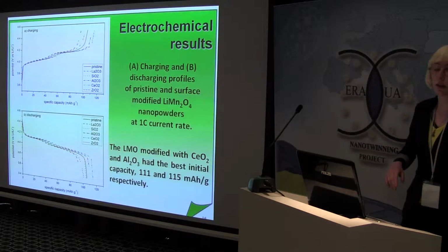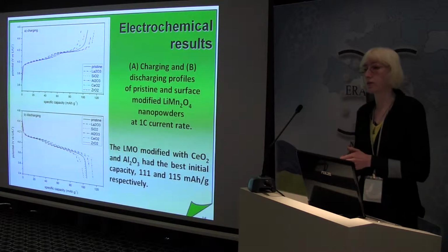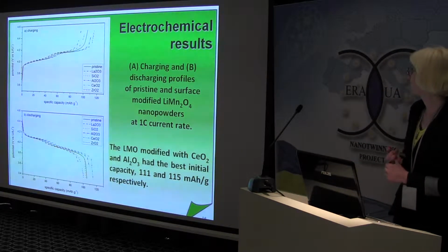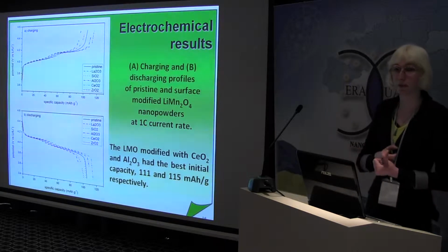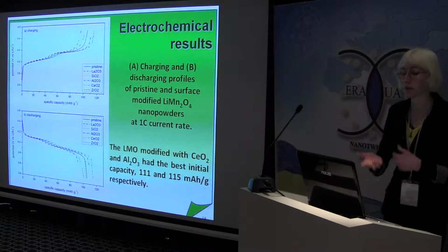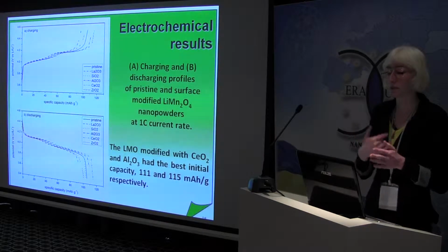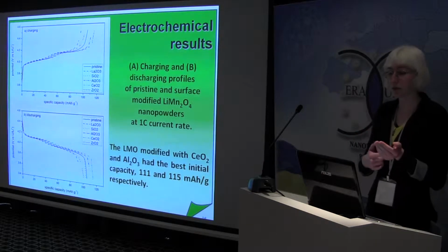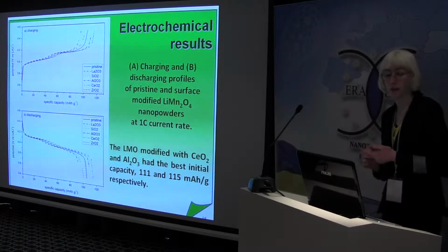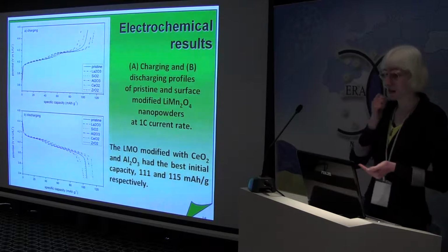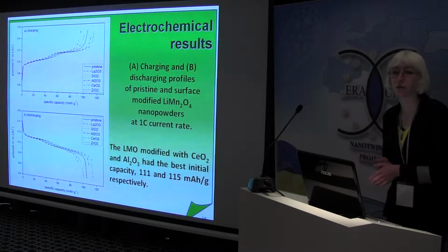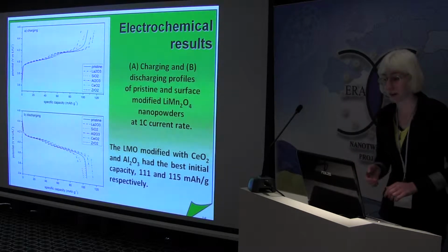We also did the electrochemical tests. So the electrode system was 3 electrode. The positive electrode was lithium manganese oxide or lithium manganese oxide modified with ceramic oxides. The negative and reference electrode was metallic lithium. And the electrolyte was lithium hexafluorophosphate.